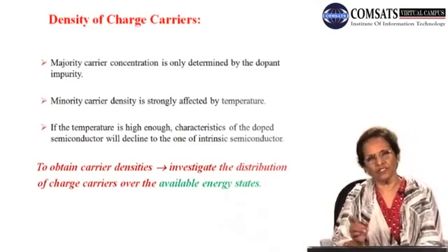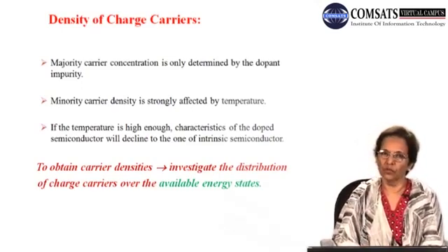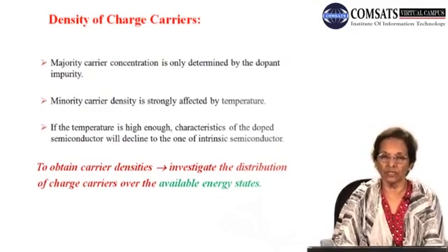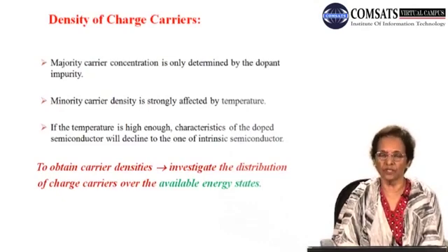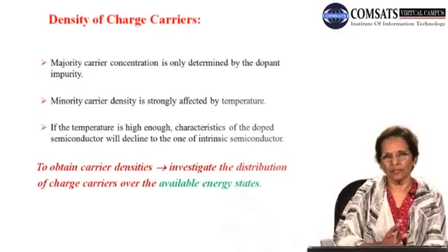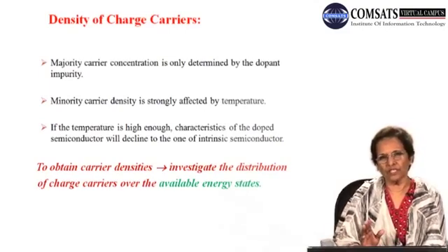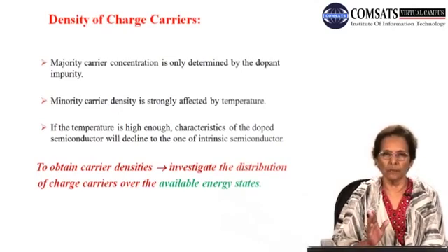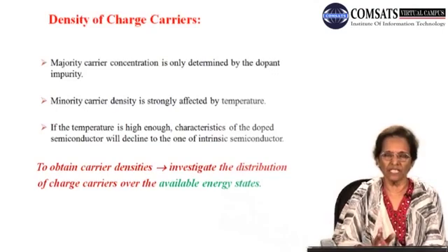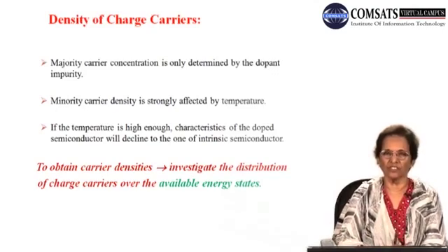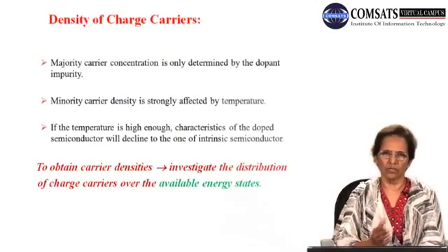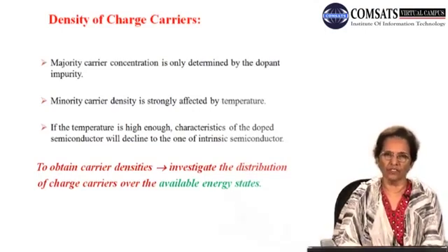So the minority carrier concentration can be exploited by enhancing the temperature. In other words, as we increase temperature, the increase in the minority carrier concentration would be larger than in the majority carrier concentration.